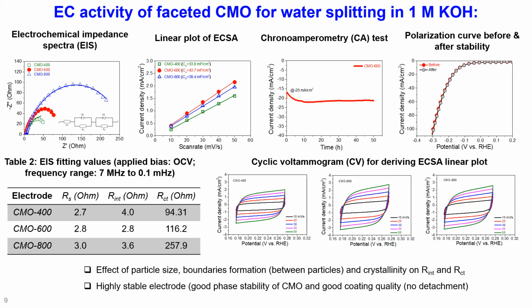And then the polarization curve before and after the stability run for the CMO 600 electrode shows that no overpotential increase or current decrement is associated with the CMO 600 electrode even after 50 hours of electrolysis.